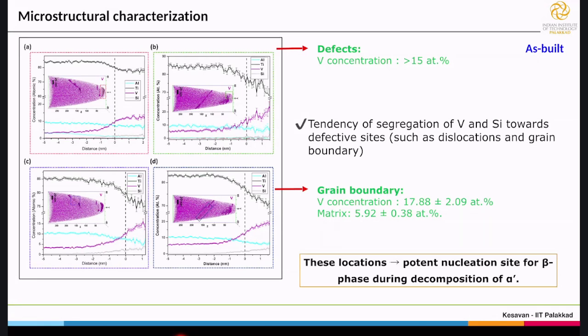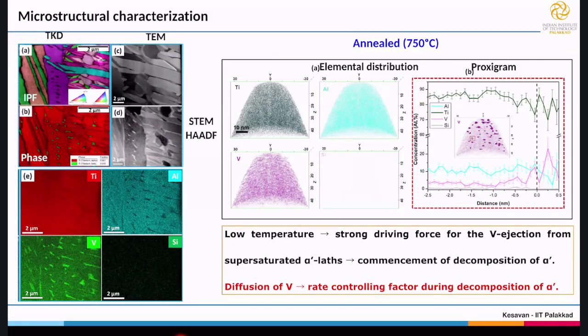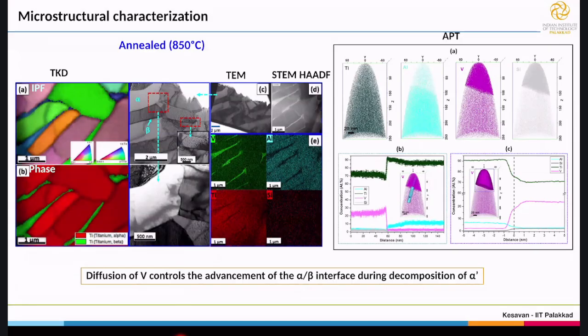So upon heat treatment, what happens? These are the regions where the beta phase started coming out. For example, you can see here heat-treated samples at 750 degrees Celsius, and you can see some beta phases coming out from those interfaces, wherever we have seen segregation. Those segregation regions are potential sites for the nucleation of the beta phase. At a low temperature, the driving force is different; at high temperature, the driving force is different. So you can see how the beta phase is coming out.